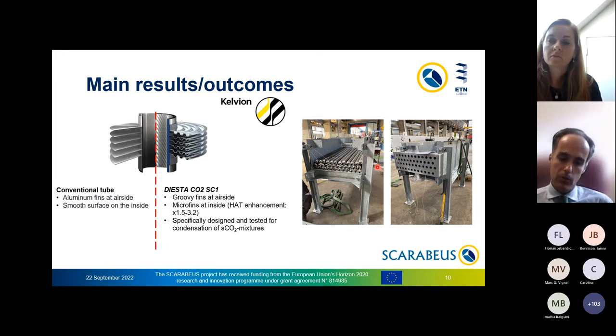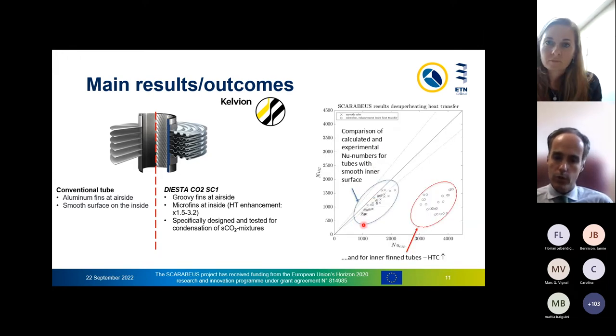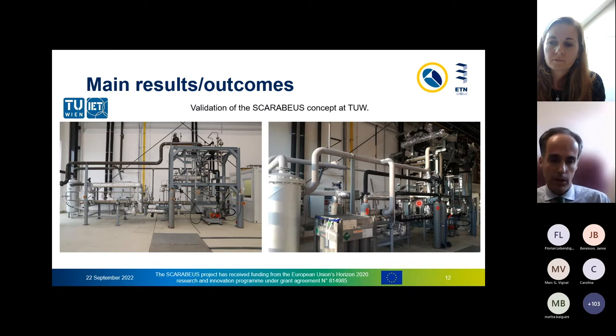Now, by using this particular geometry, what you can see here is that with respect to the standard condenser with standard fins and smooth walls on the inside, this is the theoretical Nusselt number, this is the experimental one, this is the reference geometry, this is the improved geometry. You can see that we are able to enhance the performance, at least theoretically, quite significantly. The next step is to demonstrate that experimentally. And all that experimental activity is going to be carried out at the Technical University of Vienna. This is how the rig looks like in the picture. It started off with a previous project of theirs, and we've expanded the facility.